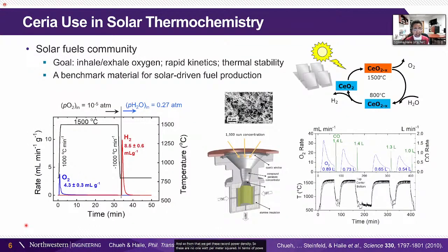Then in terms of solar fuel generation, the idea here is that we have our cerium dioxide, we heat it up to high temperatures, and as a consequence of heating it up, it releases some oxygen. We cool it back down and expose it to steam. It reacts with the steam in a way that reoxidizes the oxide and then releases hydrogen. We can do this cycle literally hundreds and hundreds of times, and we're able to produce fuel during each cycle. This is an example where we release the oxygen on heating, introduce the steam, and then produce the hydrogen as expected.